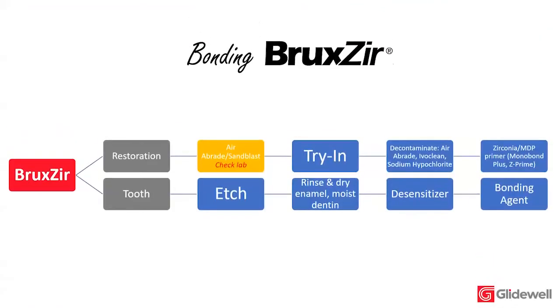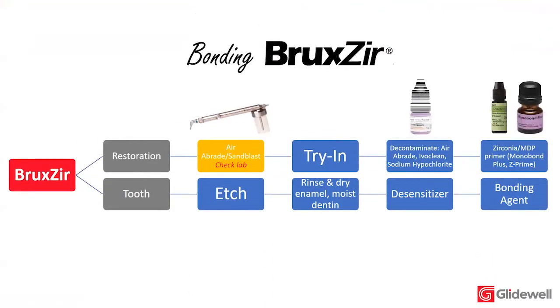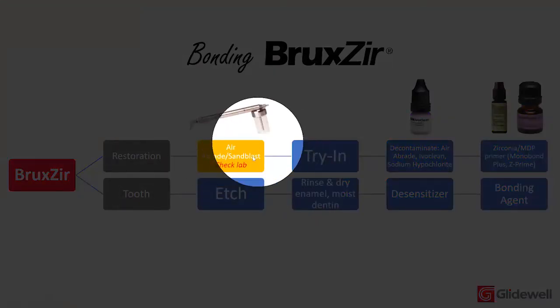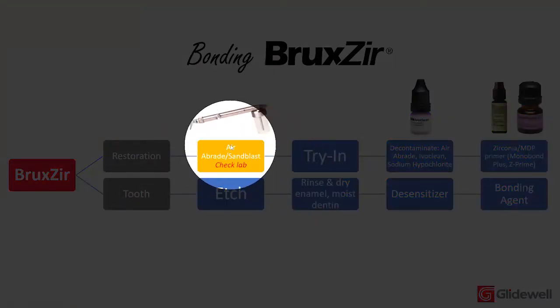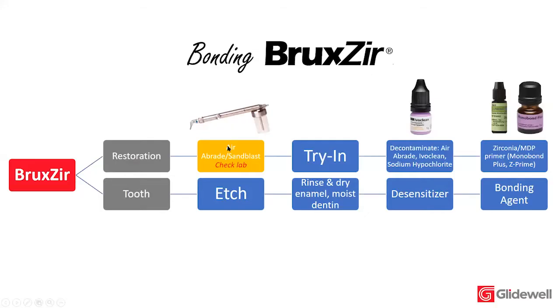Okay, so a recap of what we just did. Bonding bruxer, we need to ensure that on the restoration, the lab will usually air abrade and sandblast the restorations for you. So you really need to check. If you're not sure, please check with your lab to see whether or not they are air abrading it. Typically, we're going to air abrade those restorations with 50 micron aluminum oxide. And if they do that for you, that essentially roughens the internal surface.